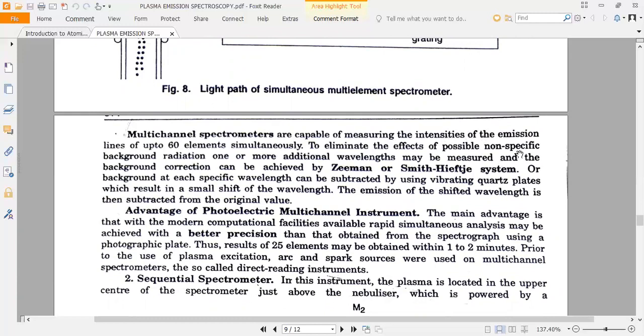To eliminate the effects of possible non-specific background radiation, one or more additional wavelengths may be measured, and the background correction can be achieved by the Zeeman or Smith-Hieftje system, or background at each specific wavelength can be subtracted by using vibrating quartz plates, which results in a small shift of wavelength. The emission of the shifted wavelength is then subtracted from the original value.